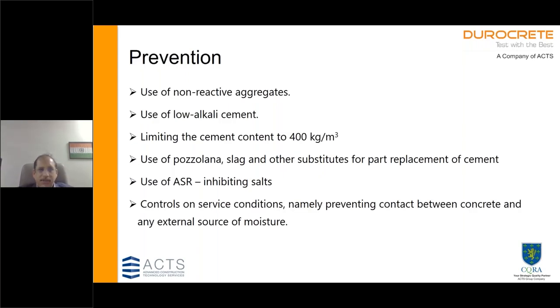So what is the prevention? Prevention is use of non-reactive aggregates, use of low alkali cements. Generally, we limit the cement content maximum up to 400 kgs because more the cement, more are the alkalis. Then it is highly recommended to use pozzolana like fly ash, slag, and other substitutes as a replacement of cement. Sometimes there are alkali silica reaction inhibiting salts that can be added.